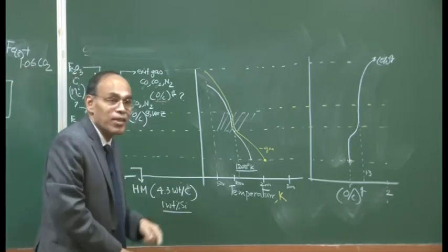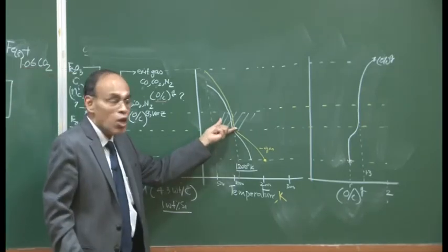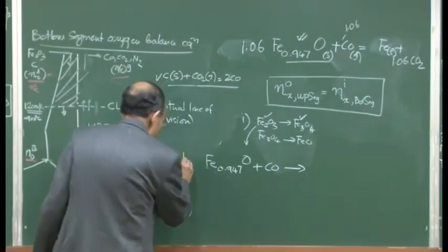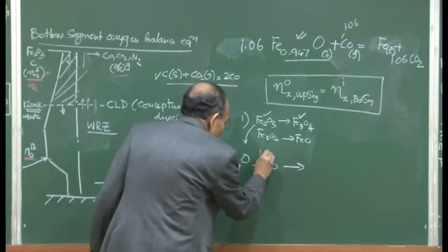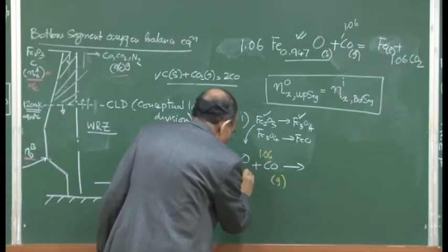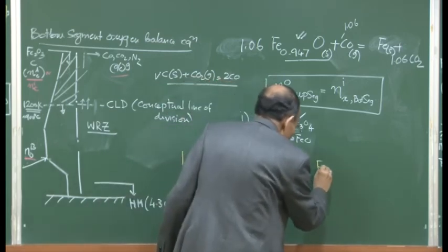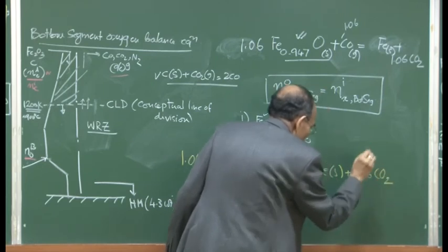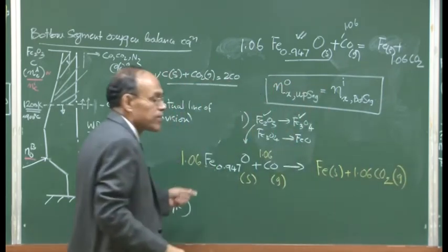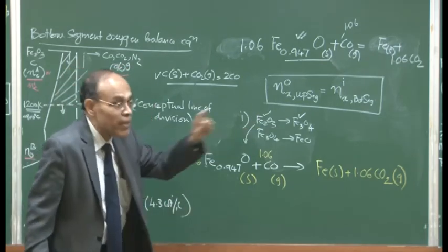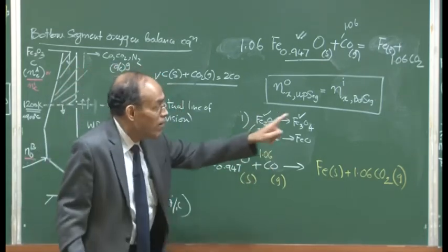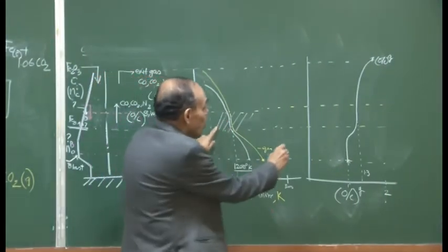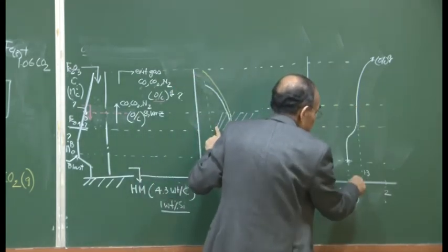And at that particular temperature, because the pressure is also fixed, you can understand that this reduction reaction which is taking place, per mole basis, I am writing again 1.06 CO2, since the pressure in that particular region is fixed and the gas and the solid have the same temperature of about 1200 kelvin, is manifested with an O by C ratio of 1.3.